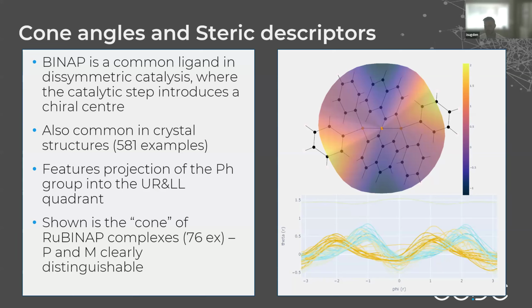And so once you introduce that type of ligand, you can then start controlling the catalytic ratio of chiral products. So the BiNAP ligand is common in crystal structures. There's 581 examples. And if you look at the picture on the bottom right, you can see that in the top right, you have a projection of the phenyl group into the upper right and lower left quadrant, which pincers and induces that chirality.